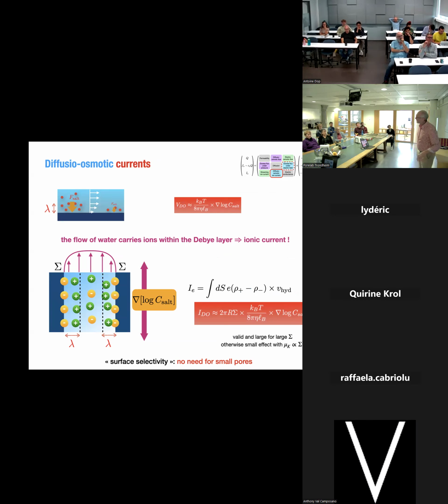This only occurs when the surface charge is very high. And when the surface charge is very small, you have basically nothing. So that was the second miracle of this experiment: it happens that boron nitride, and that was completely unexpected, has a huge surface charge, up to a fraction of a coulomb per square meter, up to 1 coulomb per square meter, knowing that glass is 20 millicoulomb per square meter. So it was very surprising.